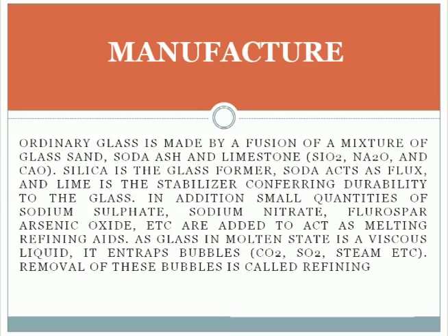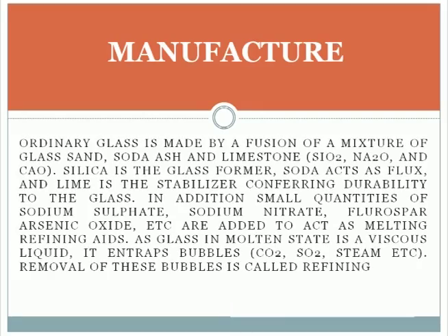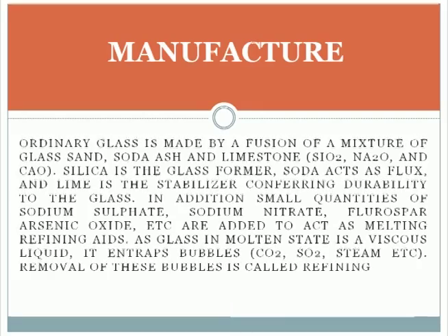In addition, small quantities of sodium sulfate, sodium nitrate, fluorspar, arsenic oxide, etc. are added to act as melting and refining aids, as glass in molten state is a viscous liquid. It entraps bubbles, CO2, SO2, steam, etc.